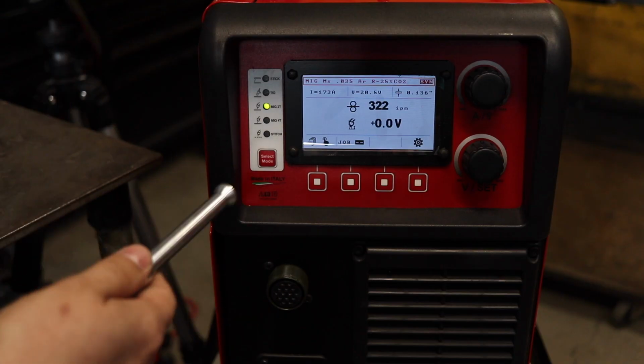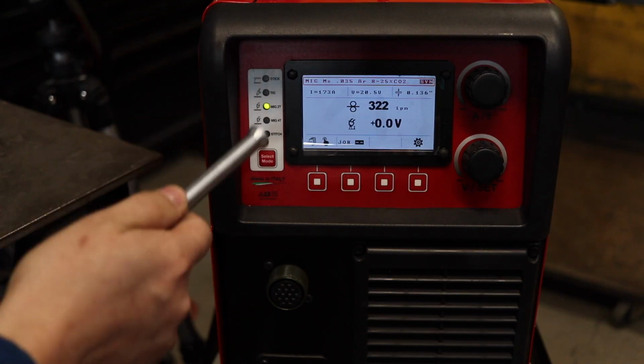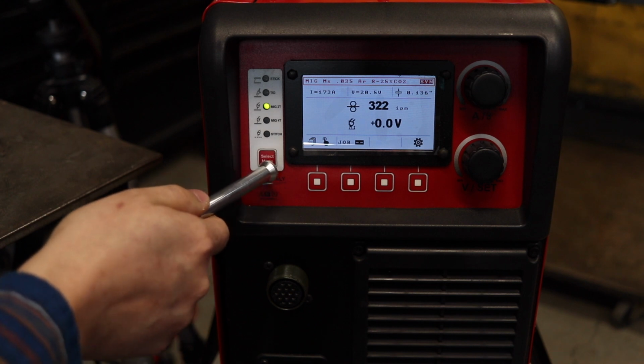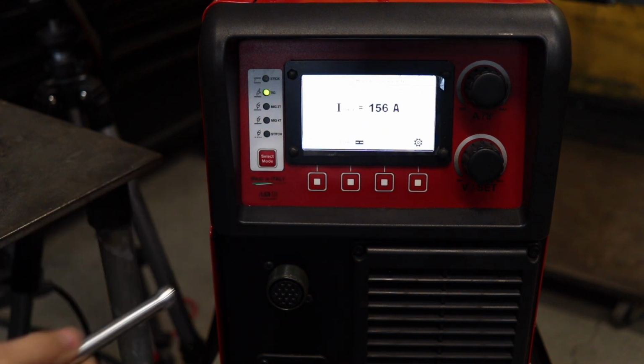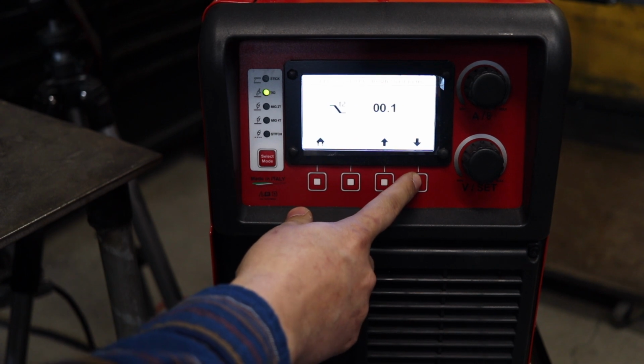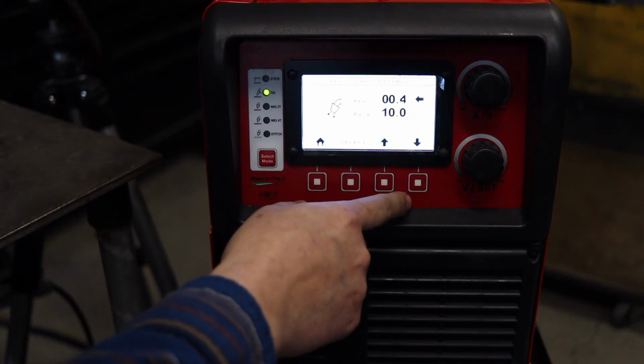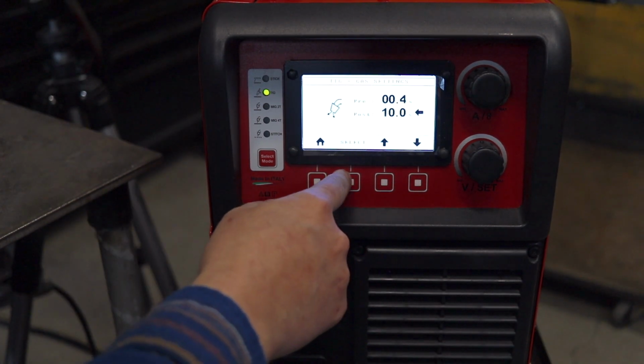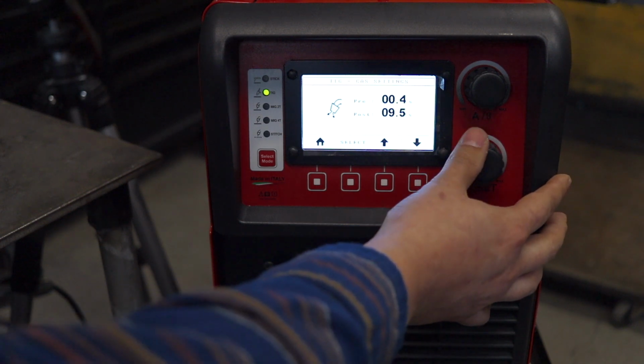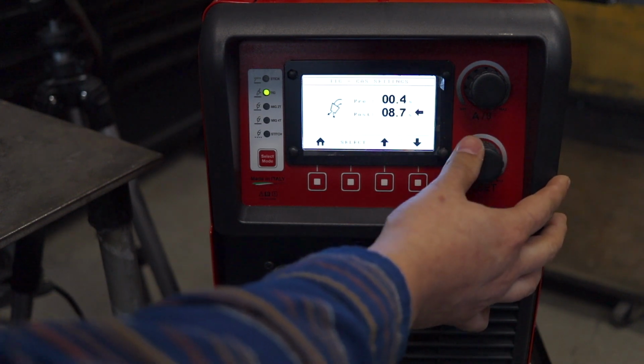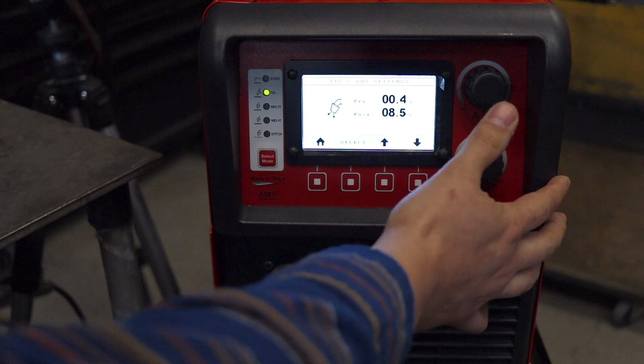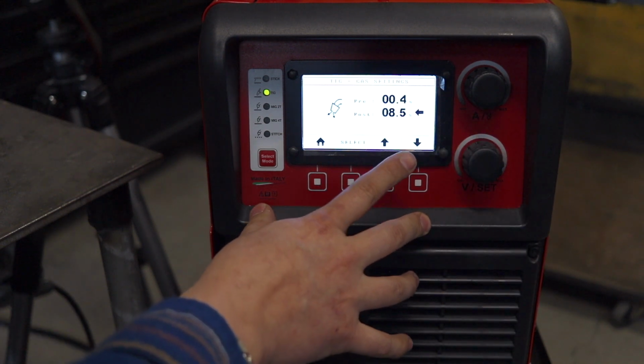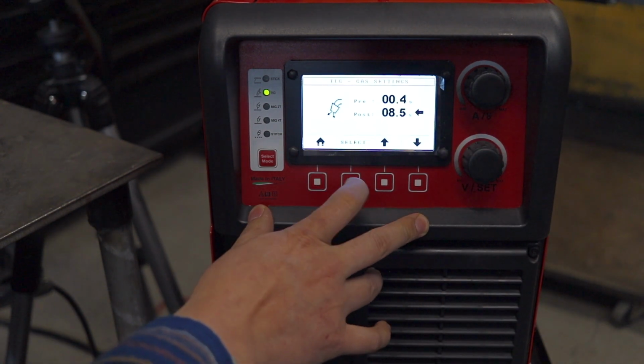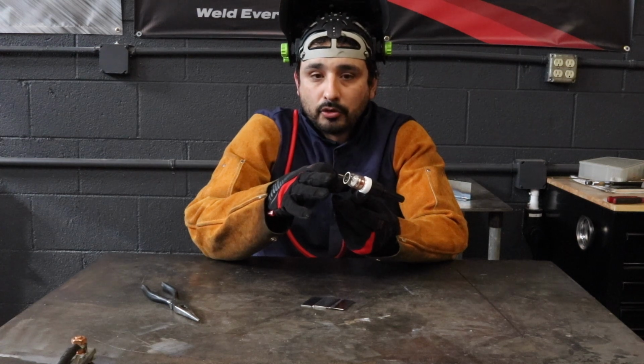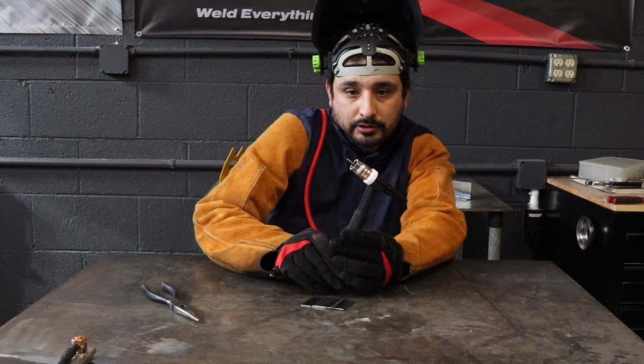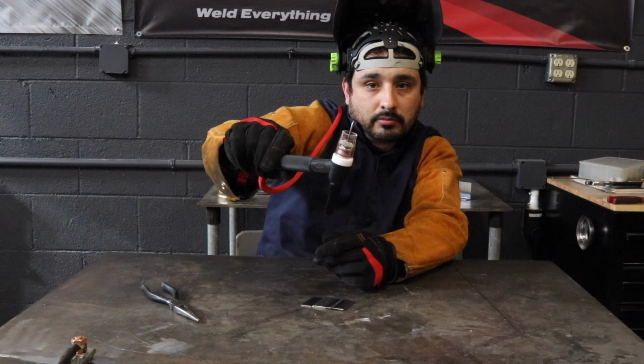Now we're going to go from MIG to TIG, and we're going to put this in TIG. So you hit the select button and get down to the TIG portion. Go into the settings, adjust your pre-flow and post-flow. In this case, my post-flow, we're going to set it roughly about 8.5. And really the tungsten's going to tell you what kind of post flow it wants anyway. This was actually 8 seconds of post flow, and you can see the tungsten, no discoloration, nice silver color.